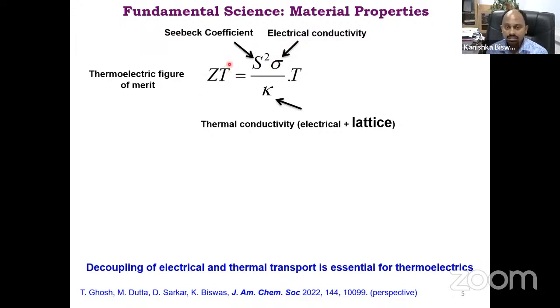In the numerator of this ZT, we have the Seebeck coefficient. Seebeck coefficient is nothing but how much voltage a material can generate per unit temperature difference, which is delta V by delta T. And sigma is electrical conductivity, which is how electrons and holes move around a solid, how fast they can go, which is directly proportional to the carrier concentration and mobility of the system. The denominator has thermal conductivity, and thermal conductivity has two parts. The first part is the electrical part of the thermal conductivity, how charge carriers carry heat in a solid. This is directly related to the electrical conductivity by the famous Wiedemann-Franz law, where kappa electronic is directly proportional to the electrical conductivity of the material.